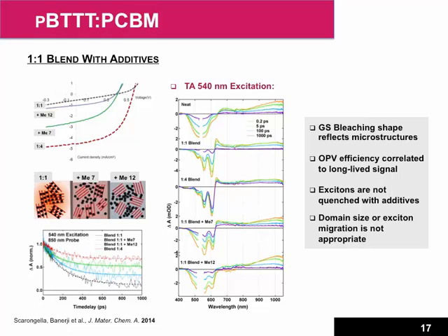So we actually had a lot of recombination of the excitons here, and we didn't get a complete yield of the charge separation. So what's limiting the solar cells with the additives is probably the size, or the exciton transport, which is not efficient because maybe the pure domains are too large, or the exciton transport is just not good enough.